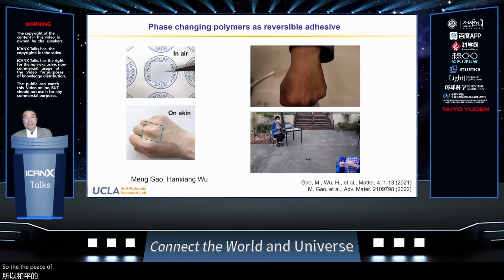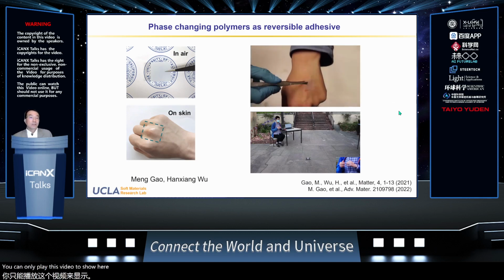The BCEP film actually has a number of other interesting outcomes. One shown here is that this BCEP film is stiff, and you can handle it easily at room temperature. But when you place it on skin, this is a specific formula where the phase change temperature has been reduced to around 28, 30 degrees Celsius. So when you place this film on the skin, the body temperature will soften it. And since the film is so soft at body temperature, it actually sticks to the skin. Let me play this video to show that this could be used as a reversible adhesive.